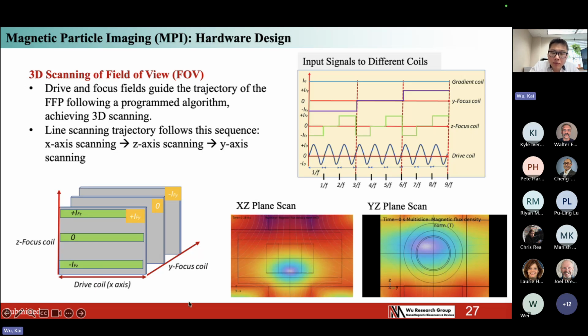Okay, so here the video shows you that we are doing the line scanning on the XZ plane, the plane facing you. We do the 3-line scanning to control the purple color field-free point, which means at each time point, only nanoparticles inside the purple region can generate the harmonic signal. We can use it for image reconstruction. We also show you the plane by plane scanning, 3 planes in the Y direction. So this demonstrates that we can control the magnetic field to program the scanning of the MPI in the whole 3D space.